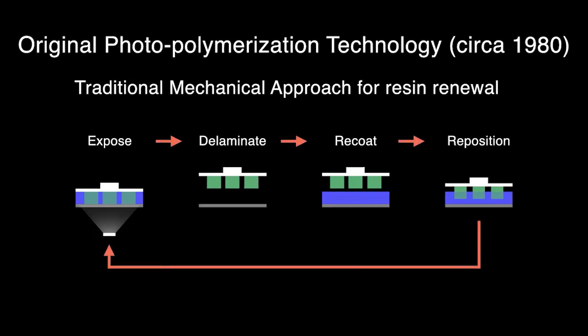So this is not so much an adhesion issue. It's two things. It's an adhesion issue and it's a mass transport issue. How do you get monomer back in there? It's not just an adhesion issue. A lot of people in the literature are forgetting that. It's an adhesion issue and a mass transport of new fresh monomer.